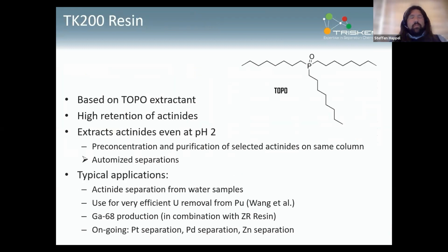Another fairly new resin that we're using, and that is getting a bit more interest, is TK200. It's a TOPO-based resin. That's quite a known extractant again. Very, very high retention of actinides. One quite particular point that I'm going to show in a minute is that it does extract a number of actinides, even at pH 2. So that is something we're looking at increasingly, to use the same resin to pre-concentrate the actinides, or any analyte really, and then purify on the same column. So that's ongoing work.